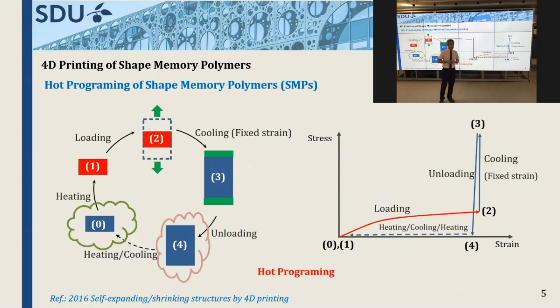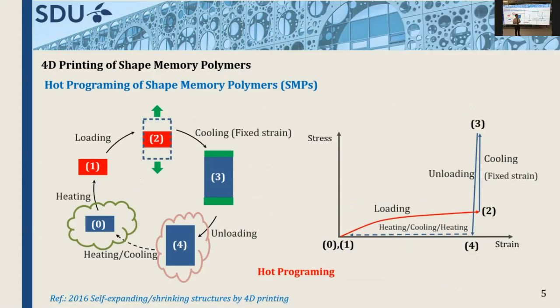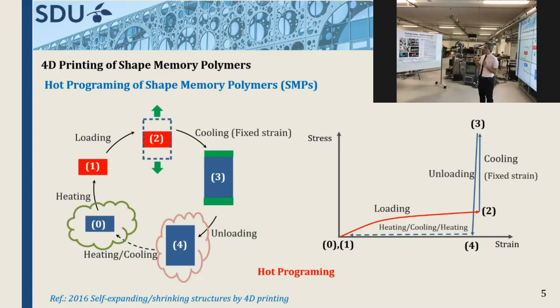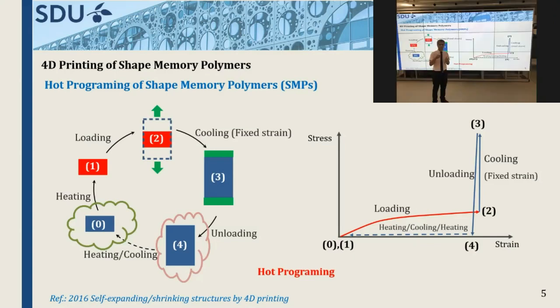Here we have a cycle of thermomechanical loading. The first feature of the shape memory effect, as you can see here, can be produced at high temperature. In this way, from room temperature, we heat the material. After that, the material experiences the loading condition. At the fixed strain, we can unload. As you can see, if you follow the diagram, during this cycle the material moves to a temporary configuration, while this configuration is not permanent, so by the heating and cooling process, it can be recovered.